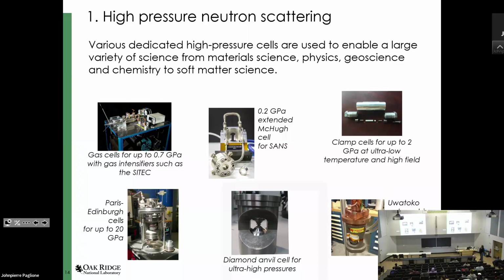Then there is a whole range of cells that are specific for SANS, where you have a different scattering geometry, so they're optimized for this. A typical cell is the so-called clamped cell, which are piston cylinder cells where you apply pressure in the press and then clamp in a nut. So this is why they're called clamp cells. These are the cells with the largest sample volume typically and are used worldwide across all neutron scattering facilities.